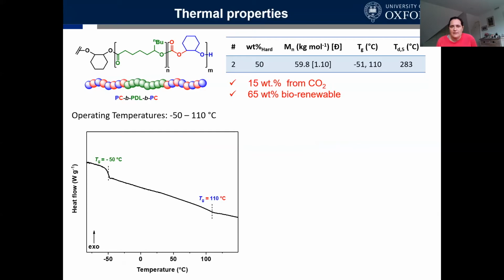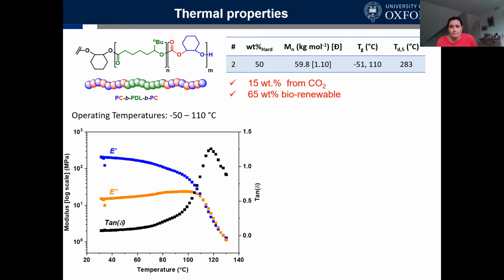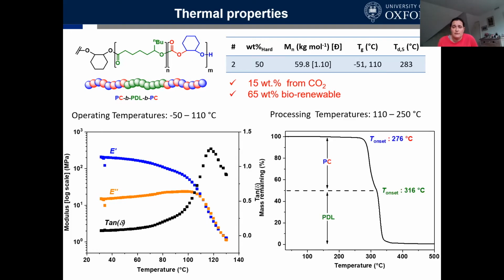So here, as I say, we have a polymer that's got 15 weight percent CO2 in it, and it's 65 weight percent bio-based because of the green block, which comes from Castellan. Here's some DMA, where we're looking at storage and loss moduli for these polymers, and again, confirming the operating temperature window up to about 100, and then a processing temperature window from 100 up to about 250. Here, a bit more on the way it degrades.